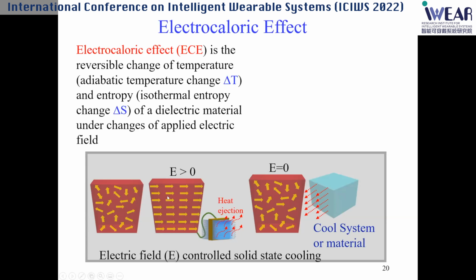Now, if you keep this at room temperature and reduce the electric field to zero, the dipoles become disordered, and in this process the material becomes cold and absorbs heat from external systems. The electrocaloric effect is quantified by the adiabatic temperature change delta T. This means when you apply an electric field under adiabatic conditions, how many degrees the temperature can change. Also, the isothermal entropy change delta S of the dielectric material.